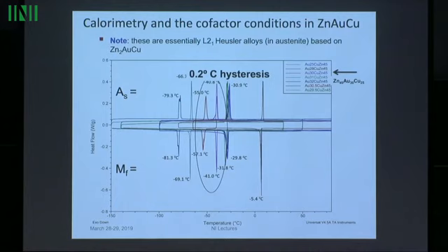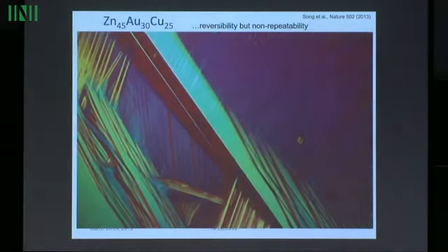And the other thing is, these nearby alloys, like this one, it's very close to this one, 28 or 20. We did quite a few tests also on 27, which is not listed here, but a very nearby composition. It's just an ordinary martensitic material. No special behavior, no special hysteresis. So again, it's very dependent on composition.